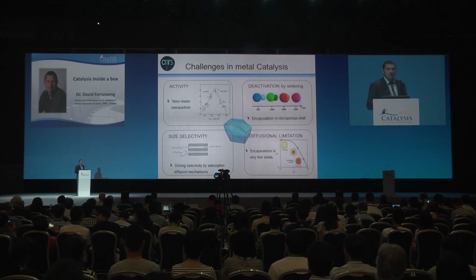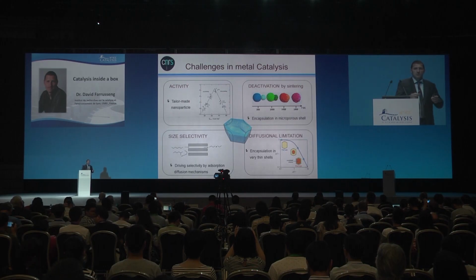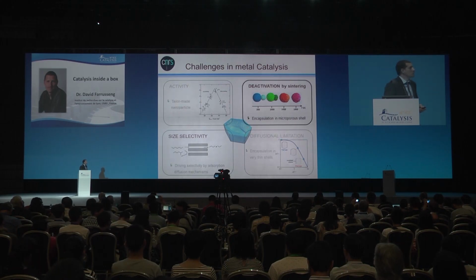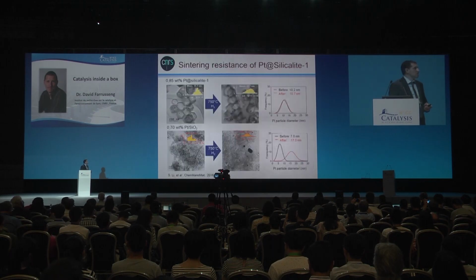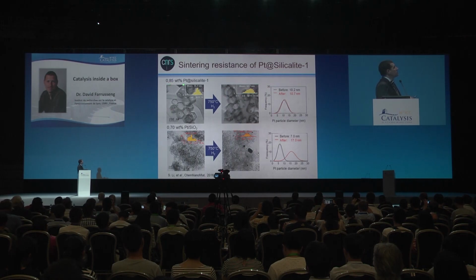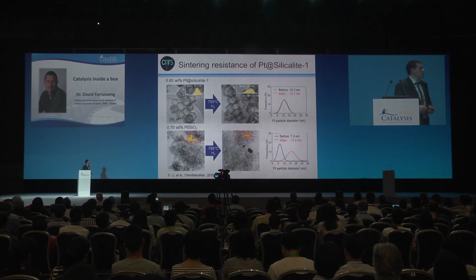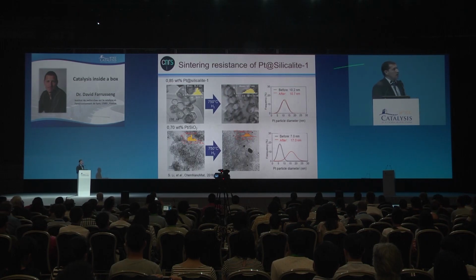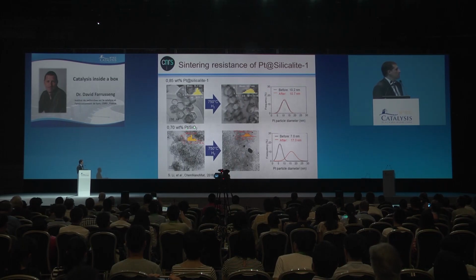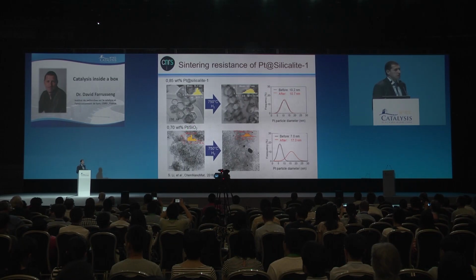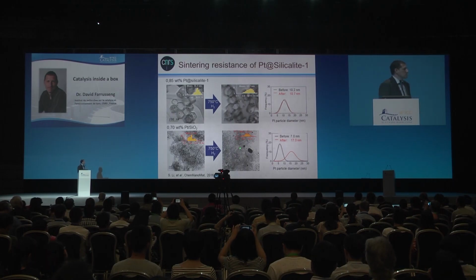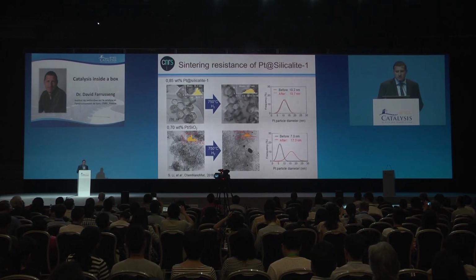But that would be pointless if those nanoparticles sinter together. So I will show how we can prevent the sintering by these encapsulations. The first example is 0.8% of platinum encapsulated in silicalite-1, and after a heat treatment at 750 degrees C under hydrogen, quite high, you can find hardly any change in the particle size. If you do the same treatment on platinum on silica, you see a big change in the particle size, from 7 to 17.